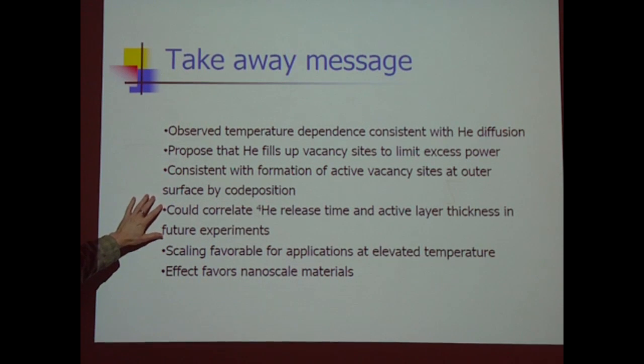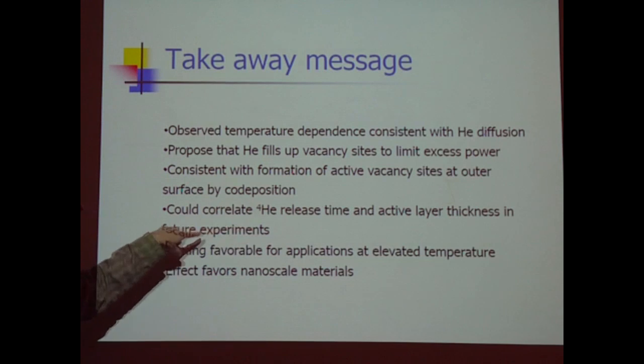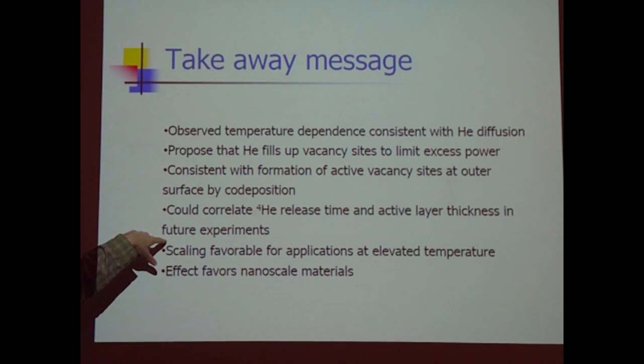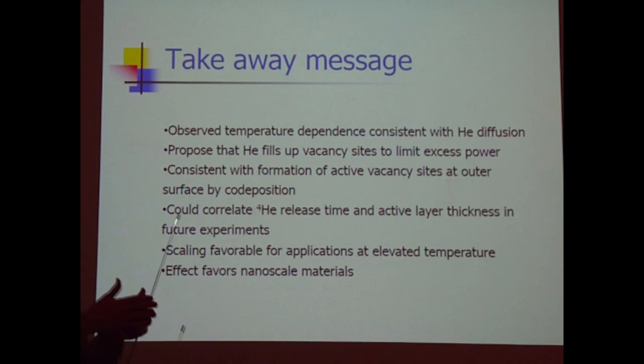In future experiments, some of my friends are optimistic and believe there's going to be resources available. I'm less optimistic, but if I for a moment entertain the fantasy that there will be resources, then in a future experiment one could correlate helium-4 release time and active layer thickness and help build up evidence. If you've got a big thick layer and you're running high excess power relative to that thick layer, is your power level limited at one point, and then you make it a factor of 2 smaller, does your excess power go up by a factor of 4?